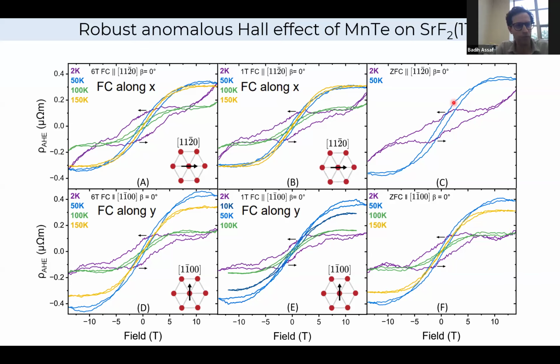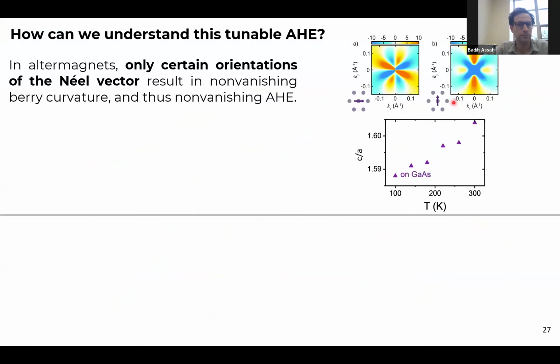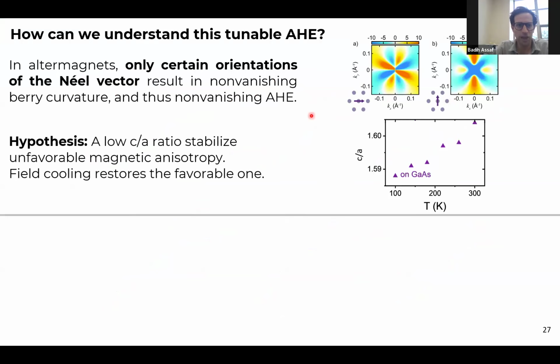So even though we don't have a full picture and an understanding of what's going on, we have a couple of hypotheses to explain it. Since in altermagnets, and specifically in MnTe, the anomalous Hall effect appears only for a specific orientation of the Néel vector, we believe that the lower C over A ratio is actually favoring a magnetic anisotropy that forbids the anomalous Hall effect. In MnTe, the anomalous Hall effect is only allowed if the easy axis is along 1, 1 bar 0, this Y direction. But if it's along the X direction, it vanishes.